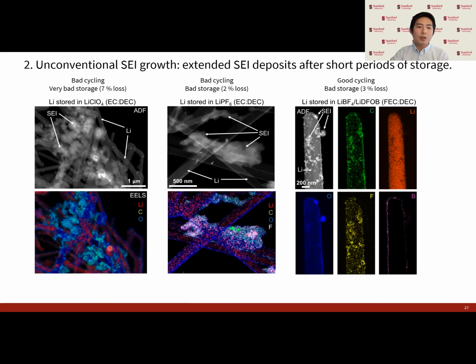So here in lithium perchlorate, which is bad at cycling and also very, very bad at storage, the extended SEI is rich in carbon and oxygen. Whereas in the LiPF6, which is bad at cycling, but better at storage, the extended SEI is rich in carbon, oxygen, but also this fluorine coming from the LiPF6 salt.